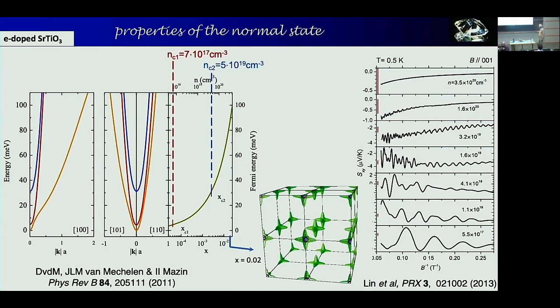And of course you can try to measure this thing. There have been many attempts, but these are much more recent data from the group of Kamran Behnia, where they measure the quantum oscillations for different dopings. So the lowest here is 5 times 10 to the 17, so you are somewhere just below that red curve over here, and then you go to higher and higher doping. And so you start to see different patterns. Of course, I'm not going to explain these data, and I hope that you don't press me on that, because this is really Kamran's business. But okay, there we are.